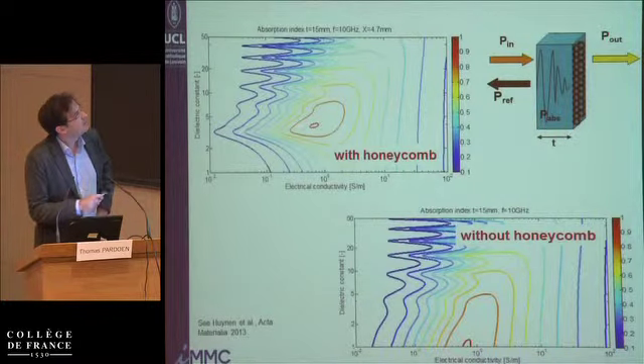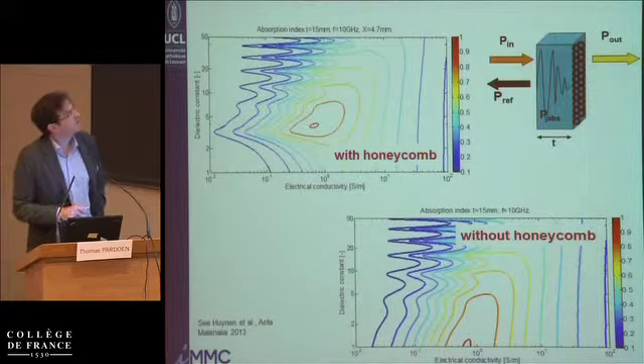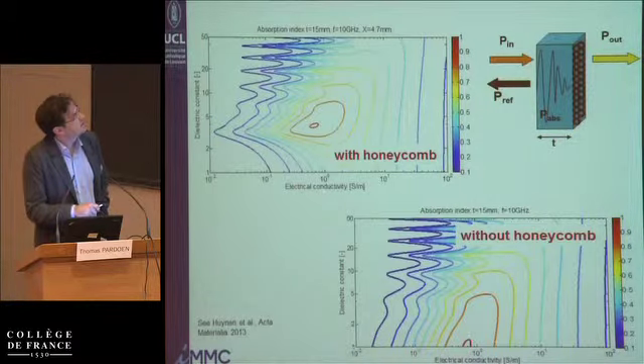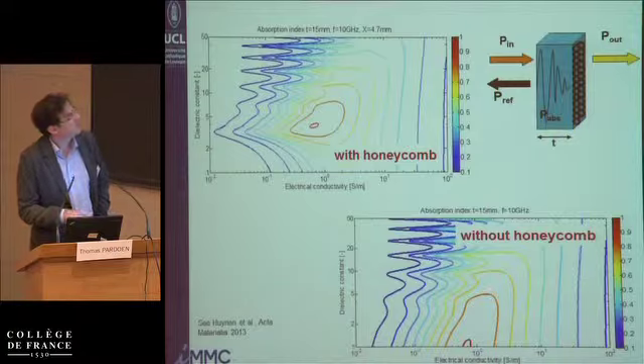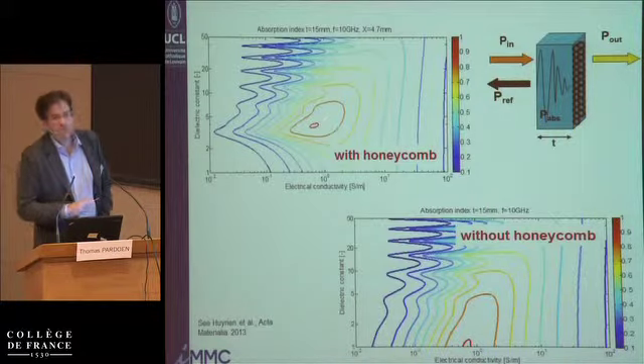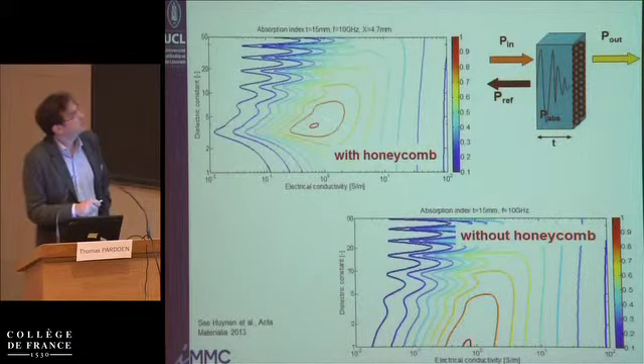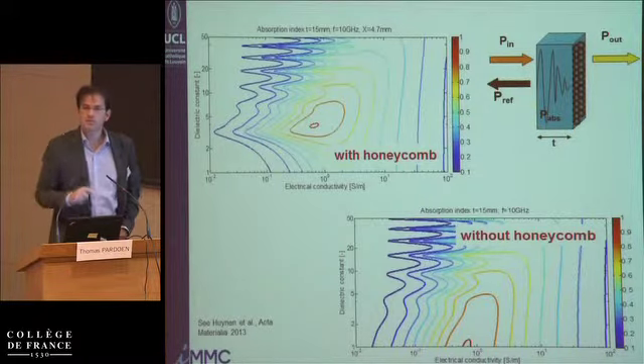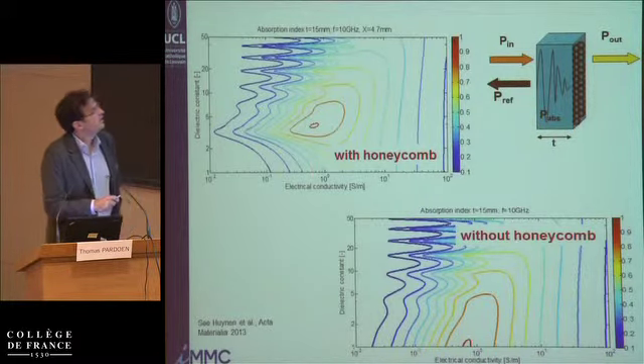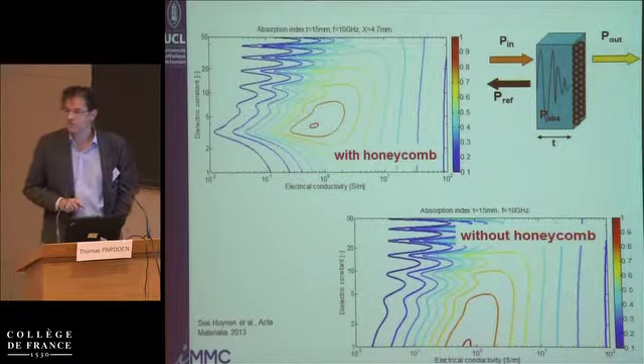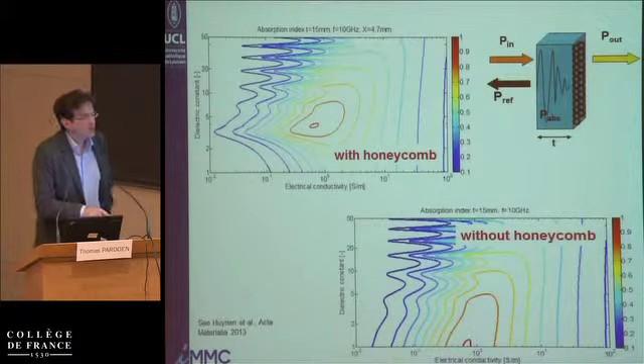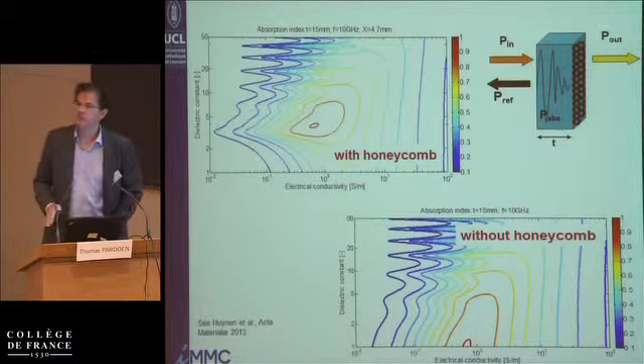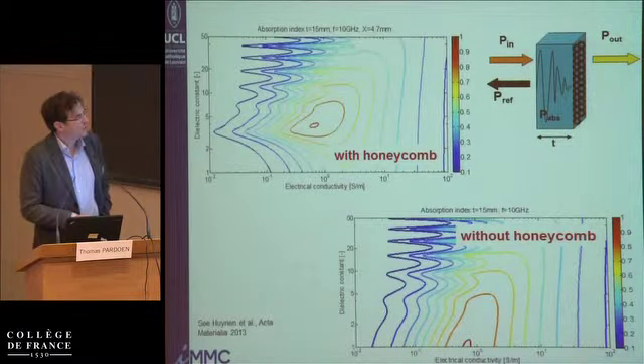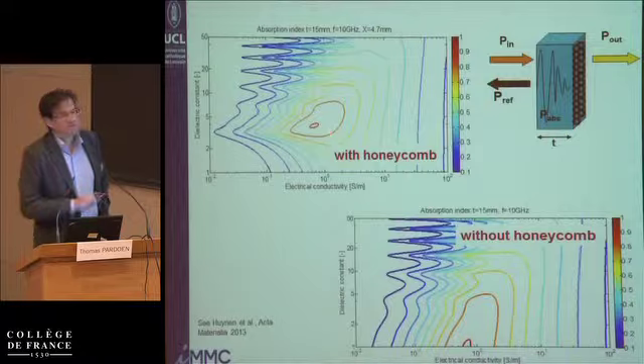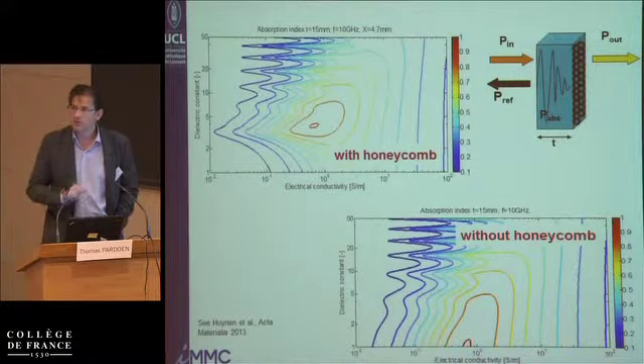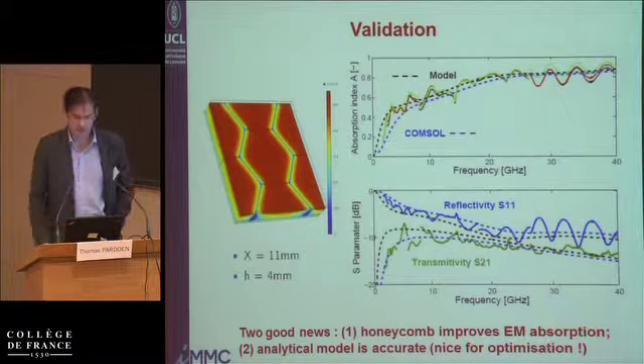If now we express the contour plot again in the same space, with the honeycomb compared to without the honeycomb, you see that the optimum effective dielectric constant of the medium, owing to the aluminum honeycomb, is moving up to values between 2 and 5. While earlier we had to reach 1, which we can't, of course. We would need open space to do that. So now it's possible to reach the optimum point owing to the presence of the aluminum honeycomb.